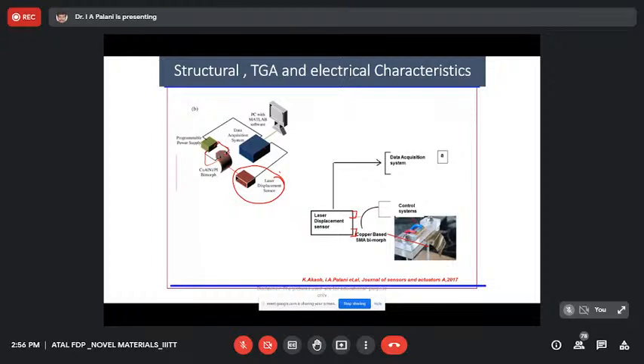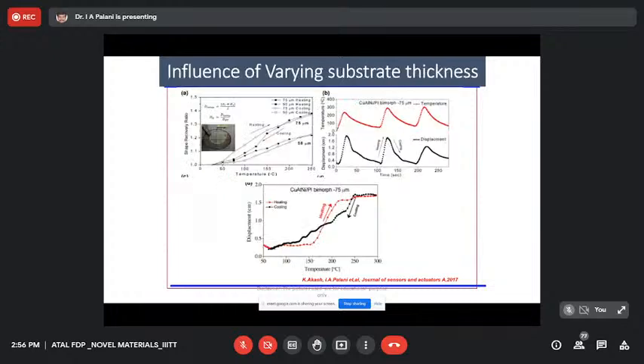We can check the frequency of the shape memory alloy, we can check the response of the shape memory alloy, and we can check the overall behavior of the system. In fact, this is the life cycle behavior of the shape memory alloy, that is, how it behaves on the heating cycle and how it behaves on the cooling cycle. This is a single cycle where heating has been performed to see how much is the maximum displacement we could see.